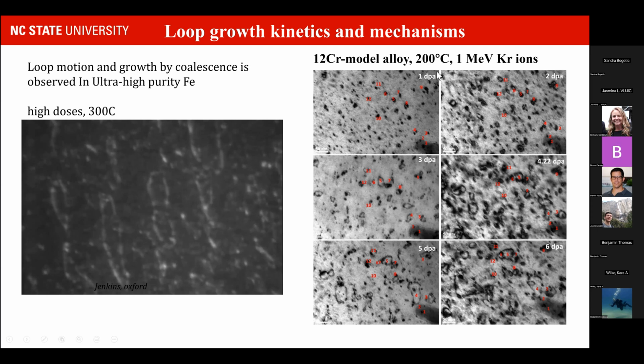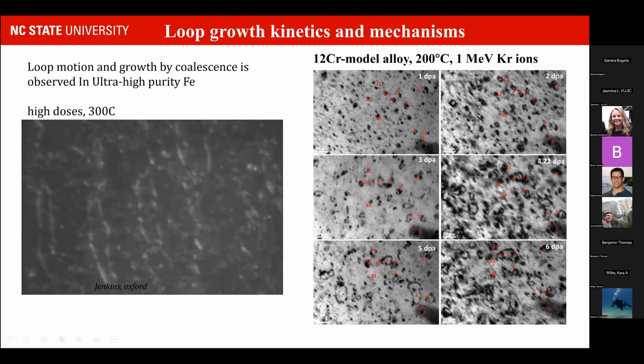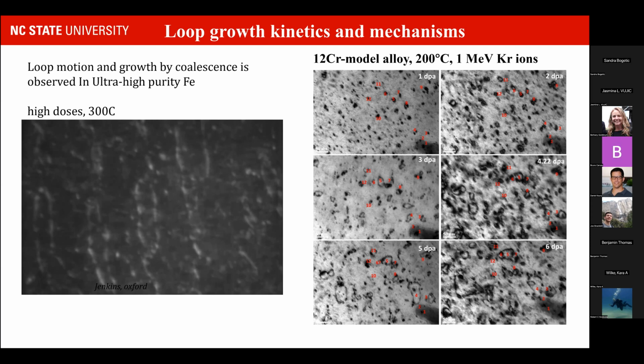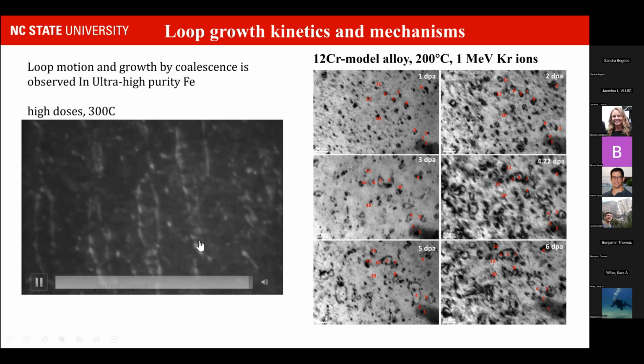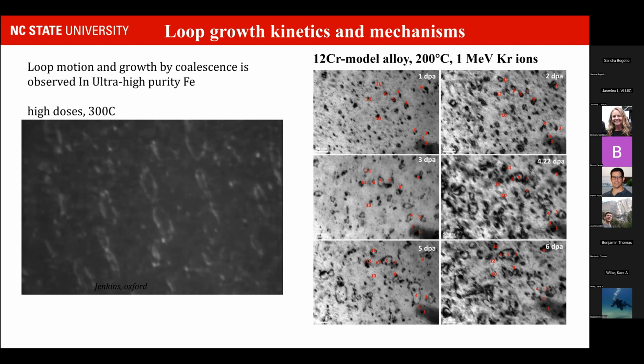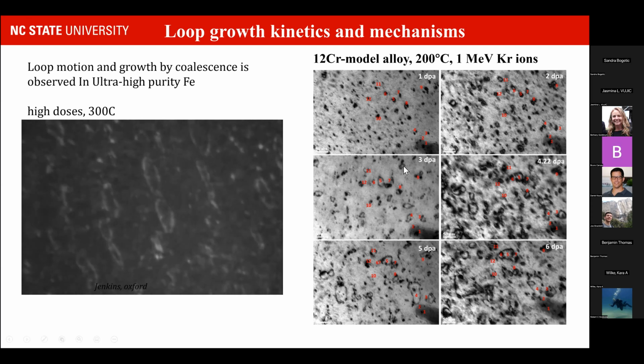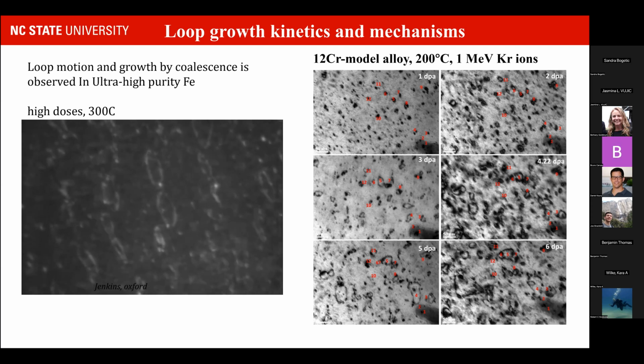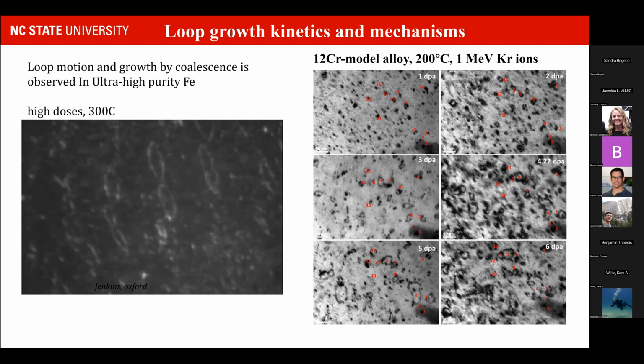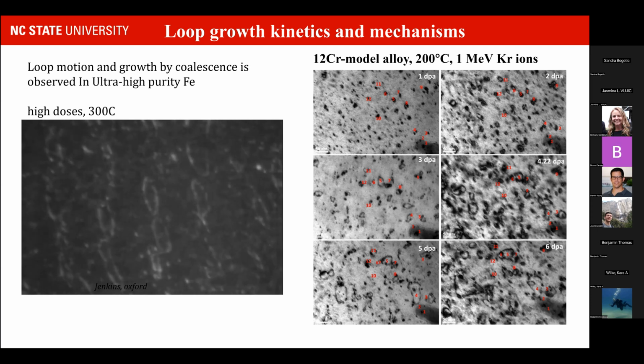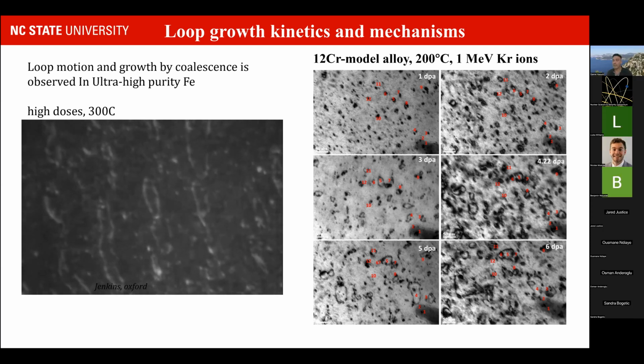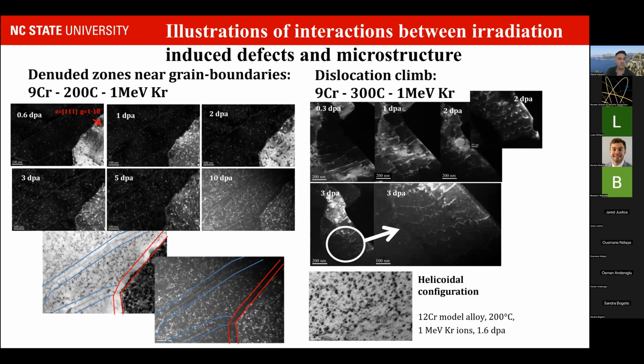And what we observe by following the loops throughout the experiment, on the right side, is that they are able to grow, but not through the same mechanism, and certainly not through coalescence of loops, because the impact of adding chromium is reducing the mobility of those loops very much. In fact, the growth mechanism is more likely to happen by a direct absorption of point defects or very little clusters that are directly formed in the vicinity of the loops. So we can also look at the dynamic, the kinetics and the growth of the loops.